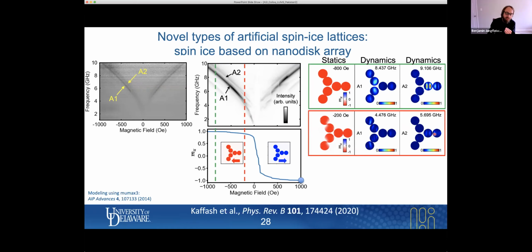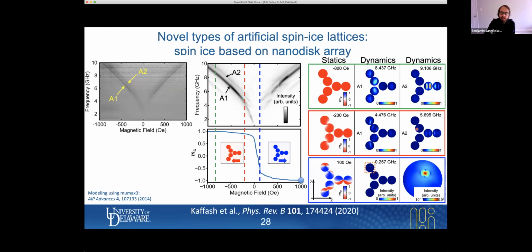Now, if we cross zero field, we indeed see the formation here, at least in the simulations, of a vortex core. So this is a flux closure state. And we also saw in the simulations this gyrotropic vortex motion at 257 megahertz. And this is just a zoomed-in version of this gyrotropic motion.